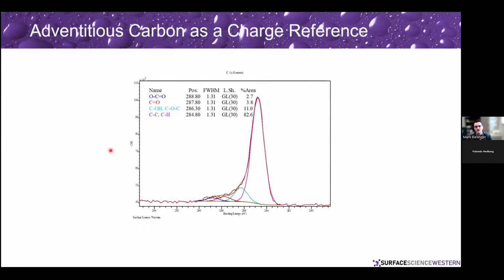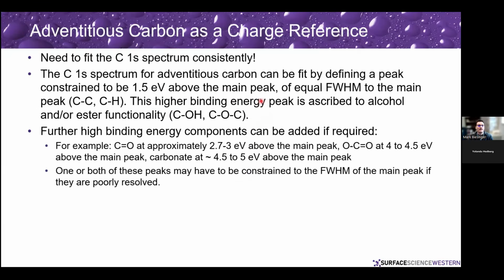If we look at adventitious carbon as a charge reference, again, we're going to do a curve fitting of the carbon 1s peak, and this is a standard setup of a curve fitting where we have our carbon main peak, carbon singly bound to oxygen, carbon doubly bound to oxygen, etc. These peaks are going to be at specific positions. We've set all these peaks to have the same full width half max, and then we've pulled out where that peak was, and we do that charge correction as I showed you earlier in CasaXPS. We need to fit that carbon 1s spectrum consistently. You can't just throw a whole bunch of peaks into there. You do have to think about what the general chemistries are.